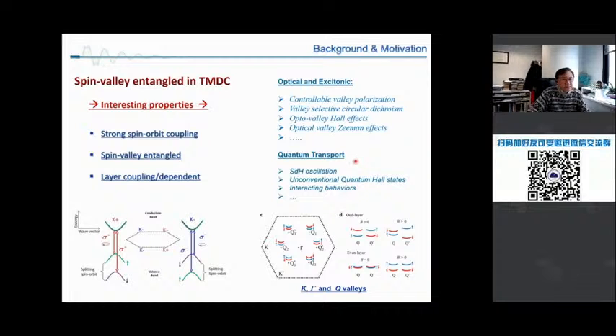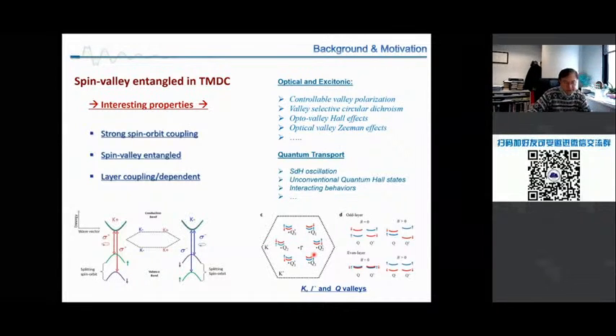On the transport study, this is the topic, the details I'm going to introduce, is that when you measure, for example, the quantum oscillations, those electron behaviors are correlated to the band structure. For example, this Q valley. People have studied the Q valley for not that long. There are 6 Q valleys, plus spin up and spin down, so the total degeneracy is 12. That means there are 12 states.